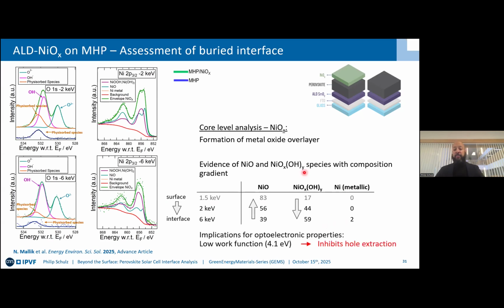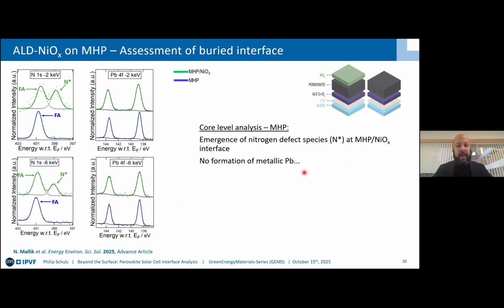Now, what are the implications for the optoelectronic properties? Actually, we also find that this nickel oxide has a very low work function, which, taken in itself and as an isolated value, makes moderate sense, to be frank, but it's also an indication that hole extraction might not be ideal from this interface. However, what is happening on the halide perovskite side?